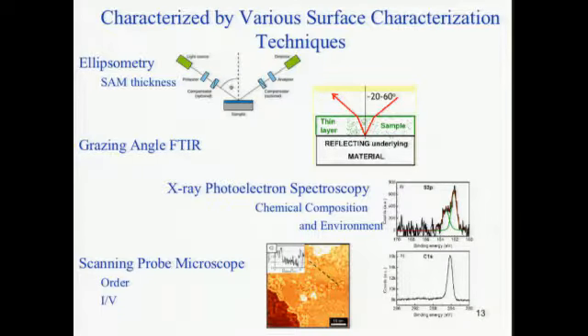Grazing angle FTIR is a very interesting technique as well. In that technique, you are using p-polarized light impinging on a reflective surface, and because it's p-polarized, you already know that vibrational modes of molecules that you look at are very distinct in their position in three-dimensional space. And it's that vibration and that distinction that helps us determine what materials we have on the surface. But now you come in with p-polarized light. Not only are you getting information about the molecules on the surface, but you're also getting information about their orientation and the degree of order.